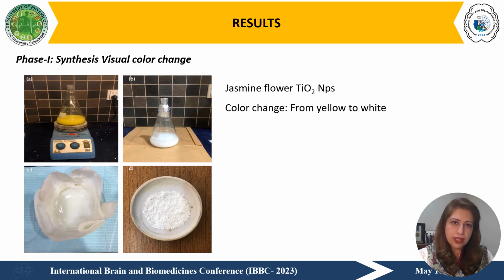Now, let's talk about the results. The synthesis in the phase 1 was depicted by the visual color change, because the visual color change of titanium oxide nanoparticles from the cream color to pure white indicated the formation of titanium oxide nanoparticles. This is being shown in the figure A, where the jasmine flower extract is in cream color, and in the figure B, the titanium oxide nanoparticles have been formed in the flask. In the figure C and D, you can see the powdered form of those titanium oxide nanoparticles synthesized by the jasmine flower.